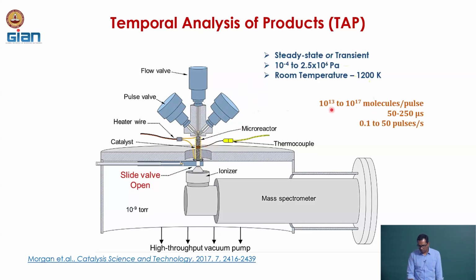Now, look at the pulse size. This is the typical range. We have 10 to the power 13 to about 10 to the power 17 molecules per pulse, and the pulse width is really small, about 50 to 250 microseconds. So, it is like a small delta function, but at the outlet of the reactor it will look like a pulse. Now, the advantage of this: if we go by Avogadro's number, 1 mole is some 6.023 times 10 to the power 23, and here we have almost 10 orders of magnitude lower. Any guess what is the typical concentration of surface atoms on any oxide, metal support or metal catalyst? Just guess a number.